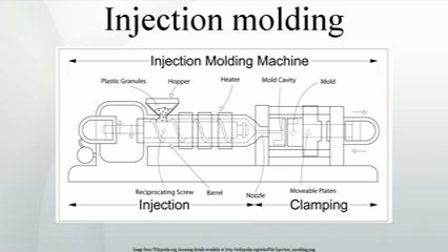The amount of resin required to fill the sprue, runner and cavities of a mold is a shot. Trapped air in the mold can escape through air vents that are ground into the parting line of the mold. If the trapped air is not allowed to escape, it is compressed by the pressure of the incoming material and squeezed into the corners of the cavity, where it prevents filling and can also cause other defects. The air can even become so compressed that it ignites and burns the surrounding plastic material.